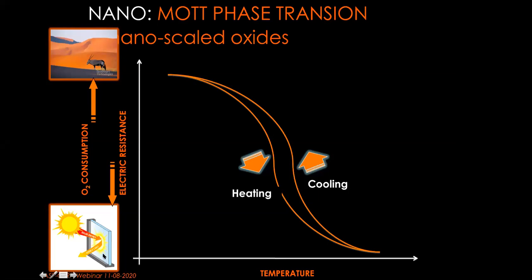And this material does it exactly like that. It has a hysteresis, and it goes from highly resistive to low resistive, low resistive to highly resistive, and so on and so on. And this material is exactly that, VO2, which has the same behavior as this gemsbok.